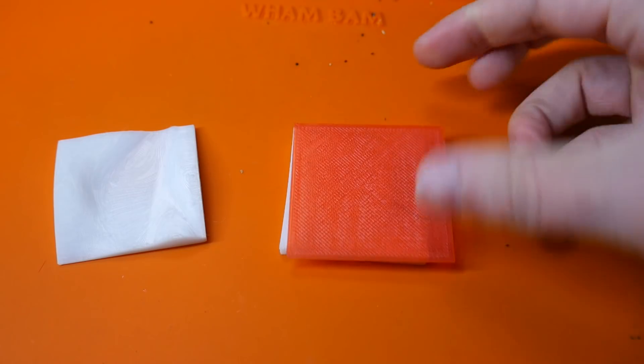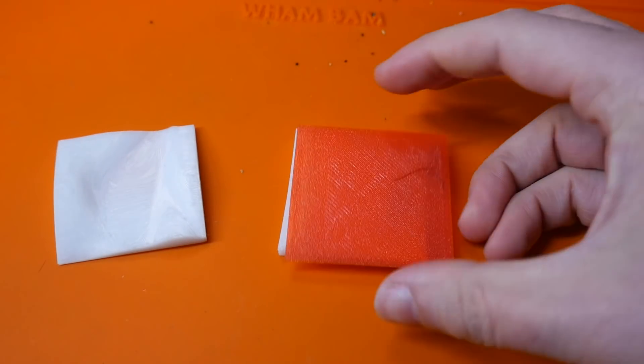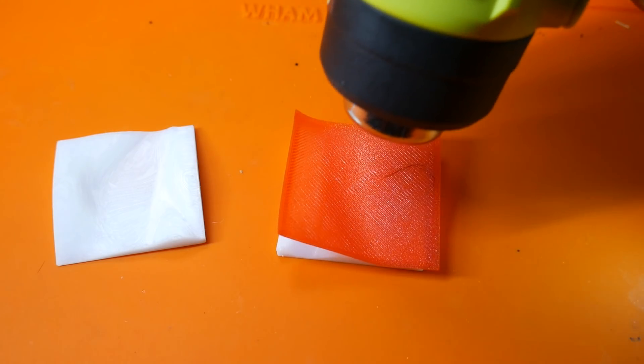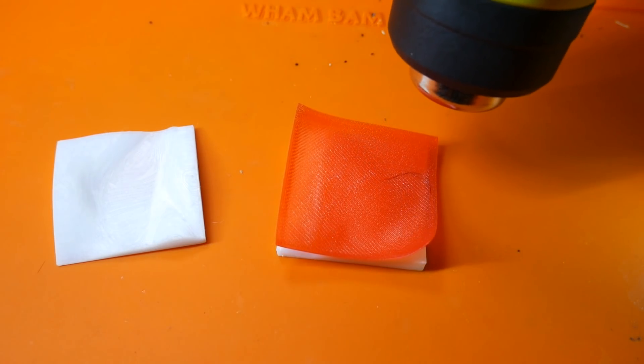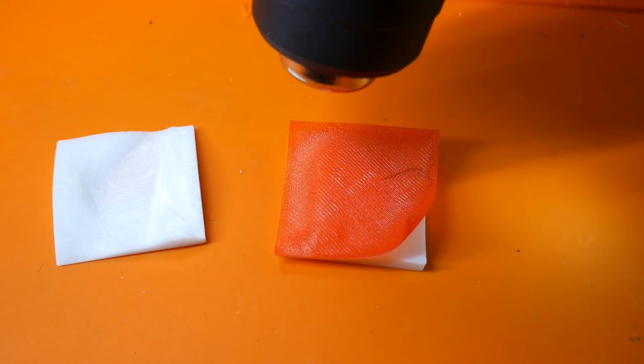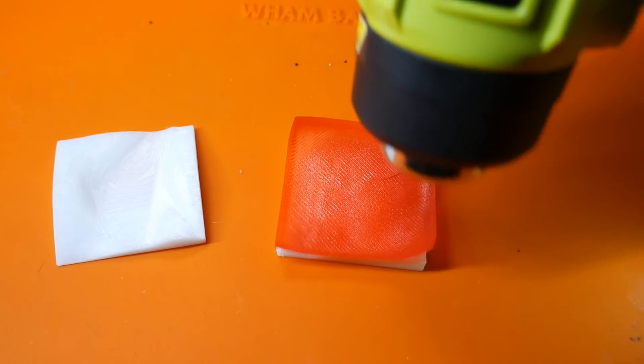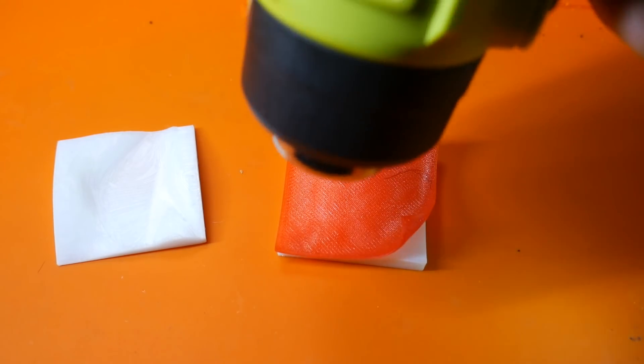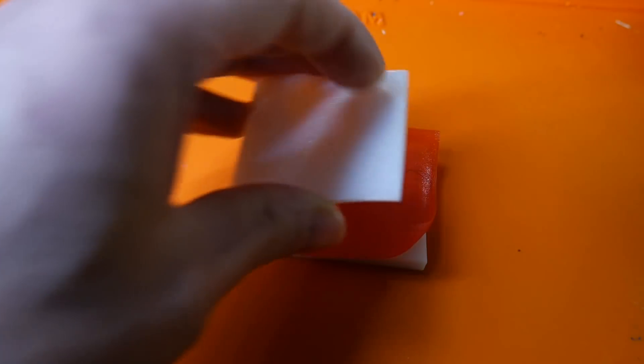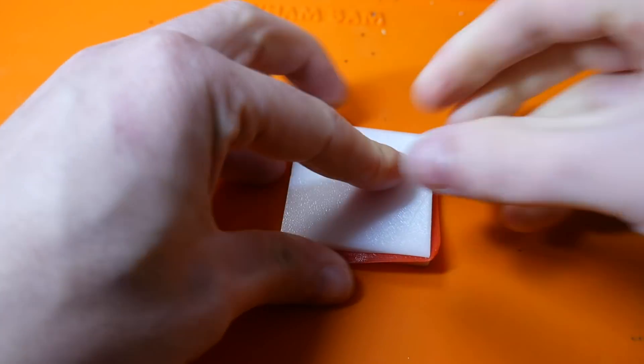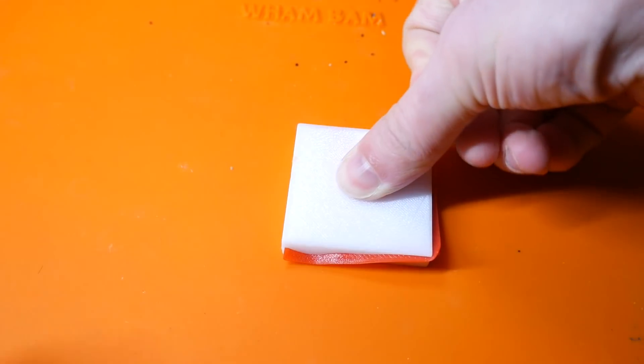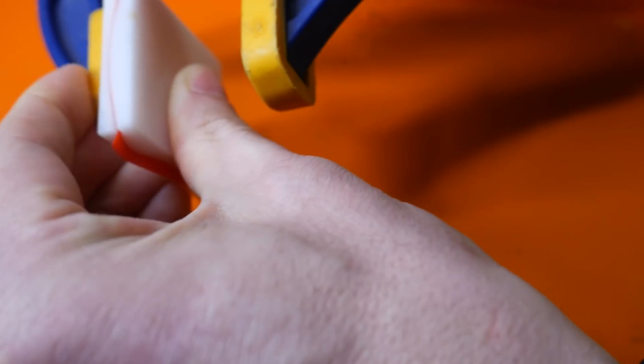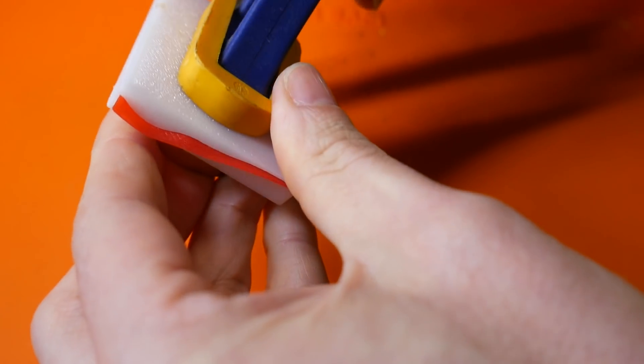Step one is to ensure that you have the two halves of the mold aligned. You don't want to get that backwards or your part will be ruined. You can then place your printed blank on top of one half of the mold, and here I used a heat gun to get it up to temperature. We're not aiming to completely melt the plastic, just to get it to around 70 or 80 degrees so it becomes pliable. If the top surface becomes very shiny and molten, you know you've gone too far. Once it's properly flexible, you can add the second half of the mold on top and clamp quickly as the plastic will cool very fast. You can put something heavy on top of the mold halves, or in my case I used a quick release clamp to maintain pressure while everything cooled down.